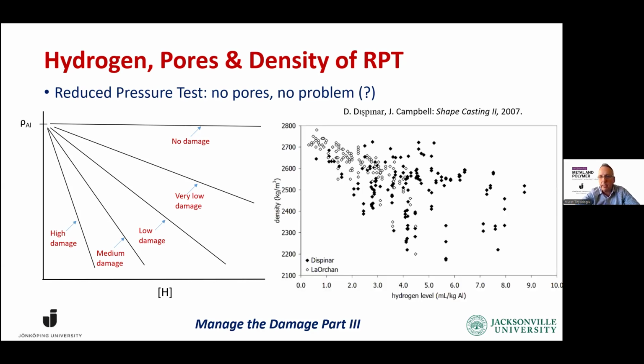And this is clearly visible in the results by Dispinar and Campbell. You can see that we can clearly identify the trends for high damage and no damage from these experimental results. So what we're doing with degassing is we're reducing the hydrogen content, but we're making the damage invisible, or we're hiding the damage. If hydrogen content is high, we can see the damage in our RPT specimens. And if we have high damage, we see a lot of pores. If we have low damage or no damage, we don't see any pores, which is a good thing. We can tell whether we have damaged melt or not.